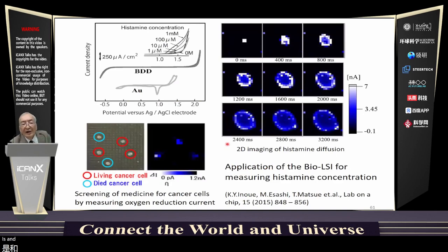Current versus potential curves of the electrode are shown in the upper left. Electrolysis occurs catalytically at low voltage with a gold electrode. On the other hand, the BDD electrode can be used in a wide voltage range for electrochemical measurement. The photograph on the right shows a 2D image of histamine diffusion measured with this bio-LSI.